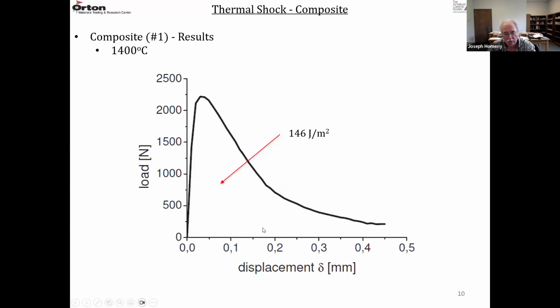So they show a typical load displacement curve. This is at 1400 degrees C for that MgO carbon material. This one is fairly strong. It tends to be nonlinear here. Then you have this gradual failure with displacement. So using the area under this curve, they calculated the work of fracture as 146 joules per meter squared.